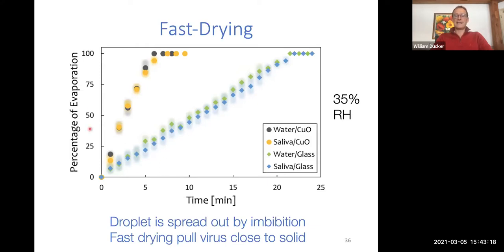It is amazing to me that this is not a known phenomenon. So Mohsen and I discovered a new chemical engineering phenomenon. I predicted in advance that because the film was hydrophilic, we made it hydrophilic so it imbibed the droplet quickly, I thought it would be harder to dry because we're lowering the chemical potential of the water, making it stick to the surface, so it would evaporate less quickly. But it evaporates much more quickly. So this in itself is an interesting bit of science that Mohsen is now studying along with an undergraduate in our department. We just stumbled upon this on the way.